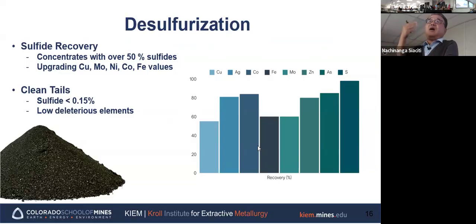And during that, copper, cobalt, nickel, arsenic even, and zinc that are associated with sulfide are going to come to the concentrate. So we make the concentrate, and the sulfide content is over 50%, and we can upgrade those base metals. And then this is the recovery of those metals. So by doing that, we can create clean tails.